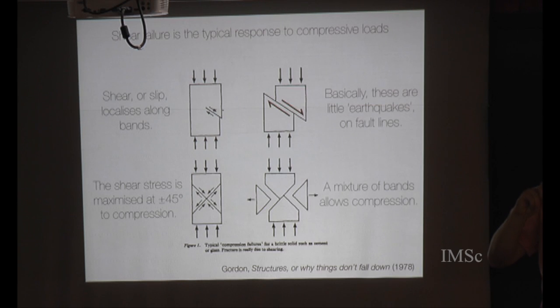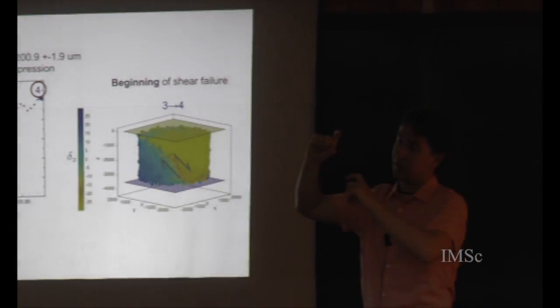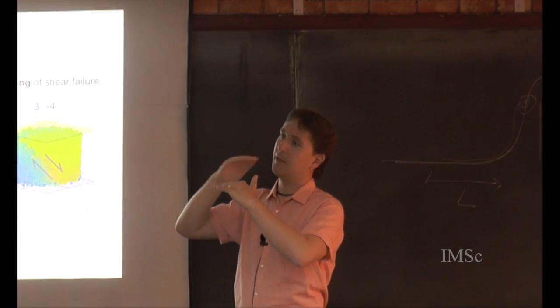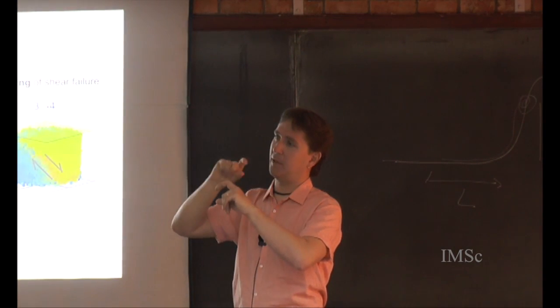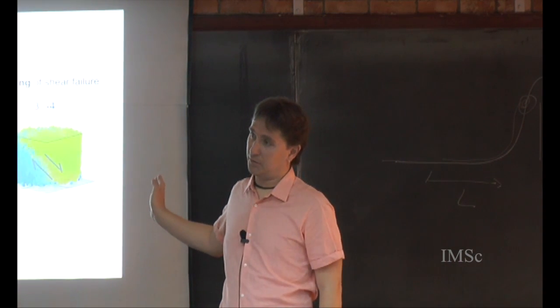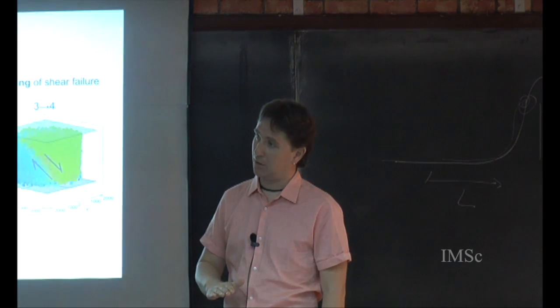And we tested that. One of our basic tests, there are two tests. One, we made one this way and then another one upside down and measured the elastic response, no change. We also made a tall sample, then sliced it into three and measured the elastic response. This is again with the largest of our beads, several centimeters high, sliced into the top centimeter, bottom centimeter, middle centimeter, and checked that. So in the samples I've shown you, there is no effect of gravity. There's no settling of the polymer to the bottom.